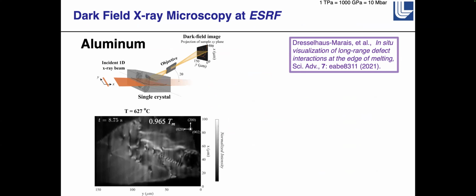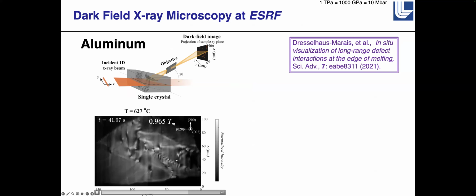Now I'm running out of time, but I'm going to go to a couple of things. This is dark field X-ray microscopy, DFXM, that Leora Dresselhaus-Marais developed when she was at Livermore. This shows a neat experiment in static aluminum at close to the melt temperature. And you can see things moving around here.